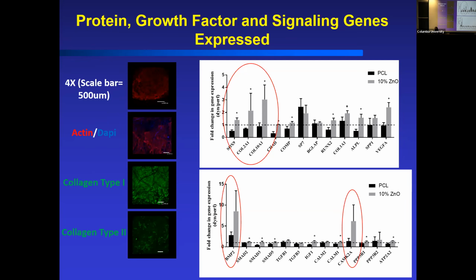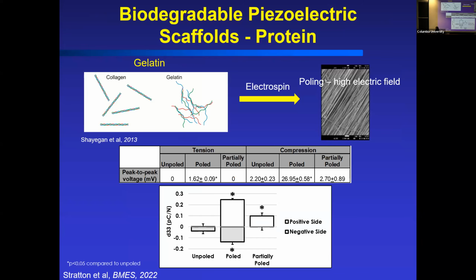We've been able to show then, in these cultures, in this media, even without the use of additional growth factors, just using these composites, these cells are producing a number of different markers for both bone and cartilage. So you're seeing here the SOX9, collagen type 2, but you're also getting gene expression for BMP2, which is going to promote bone formation as well. So it's interesting to see how that composite can affect the cells and drive them to differentiate.